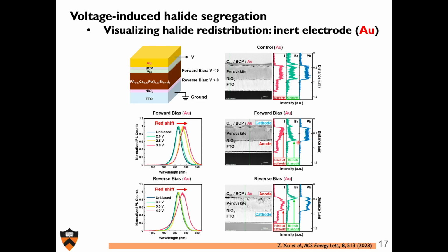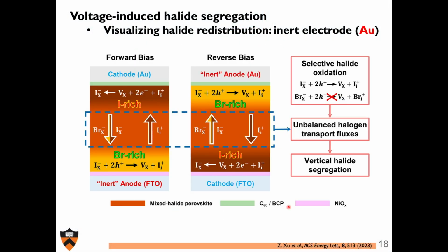If I flip the biasing, and now the top is my anode, the bottom is my cathode, you can see the reverse situation has presented itself. The bottom has become enriched in iodide, depleted at the top. The top has become enriched in bromide and depleted at the bottom. And so this draws a picture of an electrochemical cell initiating by iodide redox, oxidation on one side, reduction on the other. And this is the way we can schematically draw this. We have our anodic reaction, which is iodide oxidation, and we have our cathodic reaction, which is iodide reduction, all mediated by electrons and holes and halide vacancies on this lattice. It's a very simple closed form situation.